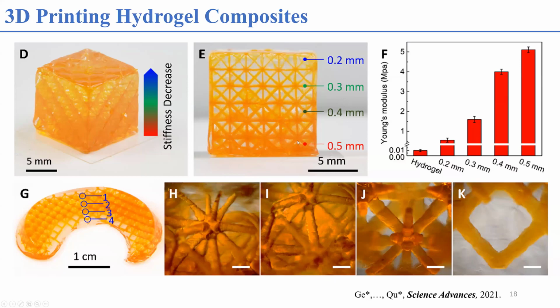And also it is 3D printing. Therefore, we can control the diameter of the lattice. And by controlling the diameter of the lattice, we can control the local stiffness. Therefore, we can change the stiffness of this structure from a pure hydrogel, which is only maybe 10 kilopascal, to the part where we have a bigger lattice, and then the modulus can be changed to 5 megapascal.